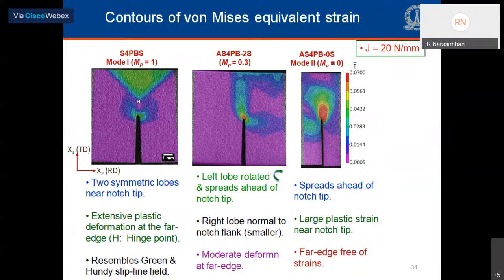These are von Mises strain contours for mode 1, the mixed mode case in the middle, and the mode 2 case. In the mode 1 case, strains develop symmetrically as 2 lobes about the notch tip on the left side. These curve around and then link up. If you see the top left side, there is a triangular region of large strain, which is caused by the compressive bending stress field. In the middle image for the mixed mode specimen, the left lobe has rotated clockwise and extends straight ahead of the tip, whereas the right lobe still remains normal to the flat surface of the notch.